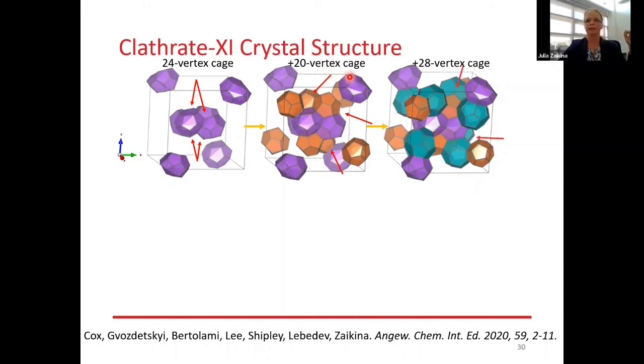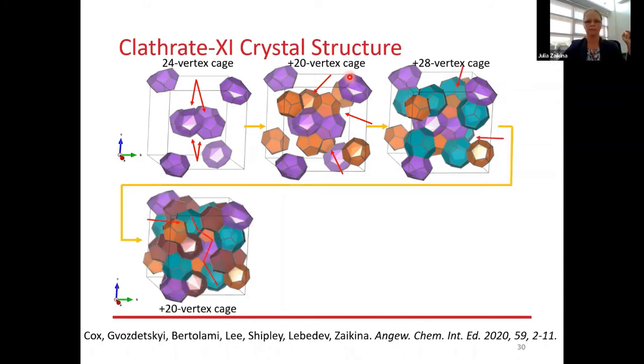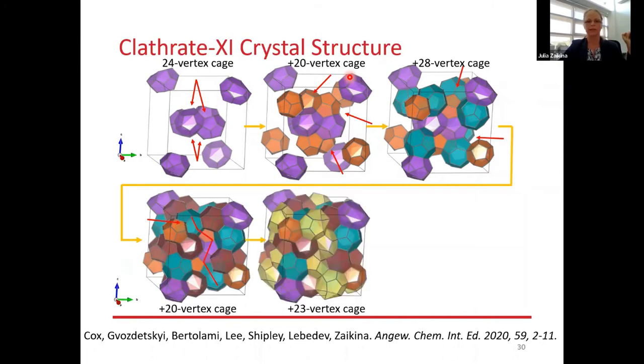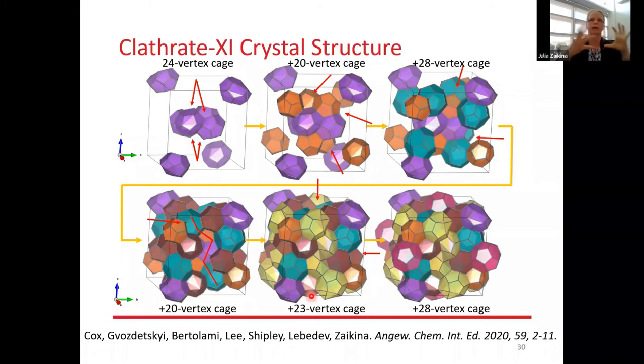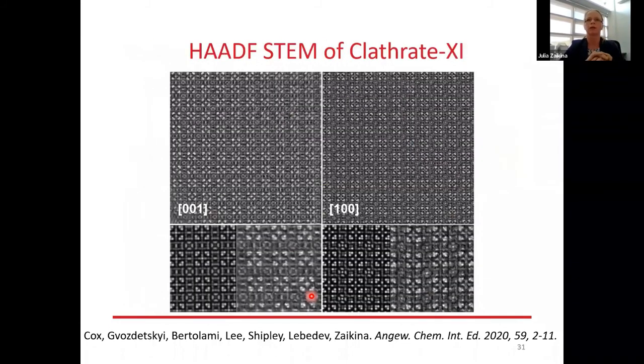And then we add 2 more types, another 20 vertex cage and a 23 vertex cage, which is not seen in other clathrate compounds, which makes this clathrate even more special. And so this builds up the whole 3-dimensional structure of our clathrate. We used transmission electron microscopy to confirm the structural model we obtained from single crystal X-ray diffraction.